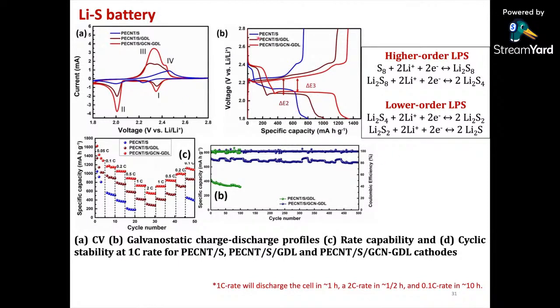You can see that the blue curve is PCNT-S only without any interlayer. We could get 800 milliampere hour per gram. With the gas diffusion layer only, we could get very close to 1100. And with the graphitic carbon nitride, it is possible to enhance the capacity very close to 1300 milliampere hour per gram. And we have done the cyclic stability as well, shown very close to 500 cycles. We have gone very close to 2C rate.